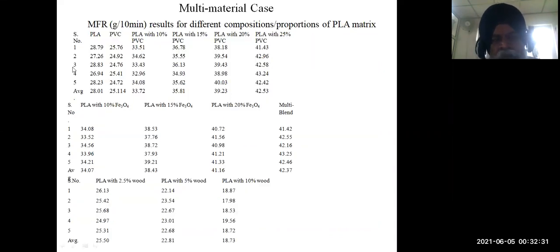Like for example, just to explain, the virgin PLA that I was using had a melt flow index of 28 gram per 10 minutes. The PVC that I procured from the local market was 25. Now, if I am adding 10%, 15%, 20%, 25%, there is a variation in the melt flow index of the material. Similarly, with the different reinforcements and with the different multi blend, I am getting a wide range of rheological properties. As an operator of my 3D printer, I am a little uncomfortable if I have to always change the settings of my hardware and software. So I have to correlate this with the proportion of the reinforcement once we are playing with the composition part, right?